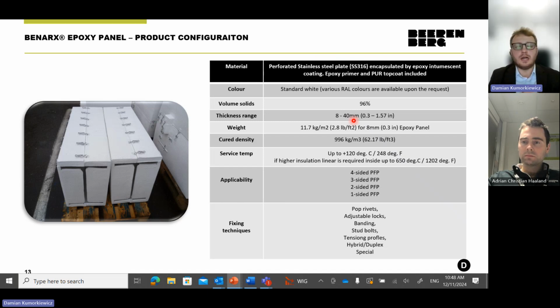However, we would like to show you our case studies from previous projects and give you better insight into our system. So this is the Benarx Epoxy Panel. It's made from a perforated stainless steel plate, stainless steel 316, which is acid-proof, and it's covered with epoxy intumescent coating both outside and inside. We also applied an epoxy primer and polyurethane top coat on top of that. Our standard color is white, but we can paint it any color. The thickness of this panel depends on the PFP rating, but it varies from 8 up to 40 millimeters for the toughest PFP specifications.